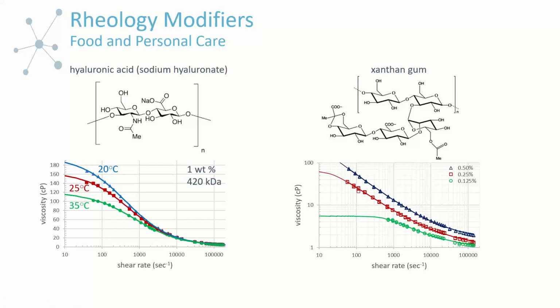So this is why it's a very attractive polymer for skincare, and then also it's used in eye drop formulations as well. And you can see on its own, so this is just hyaluronic acid or sodium hyaluronate in deionized water at 1%, the viscosity as a function of shear rate. This on its own is quite shear thinning. And although we didn't quite illustrate it here, in addition to varying temperature to vary the rheological behavior. So here we're spanning between relevant temperatures for either say eye care products or personal care products, from say cold room temperature to skin or eye temperature.